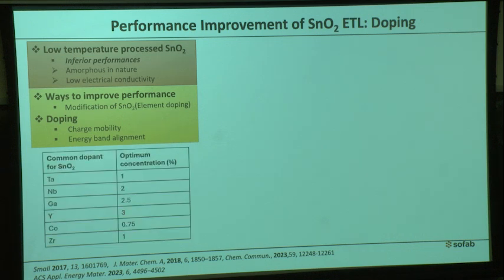We went through the literature and found a couple of elements which we can use to mix with tin oxide. Based on the literature, we found yttrium is a suitable candidate. There is more literature supporting it, and also yttrium is not going to change the color of the tin oxide.